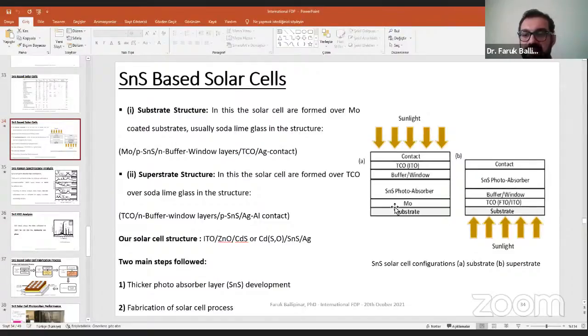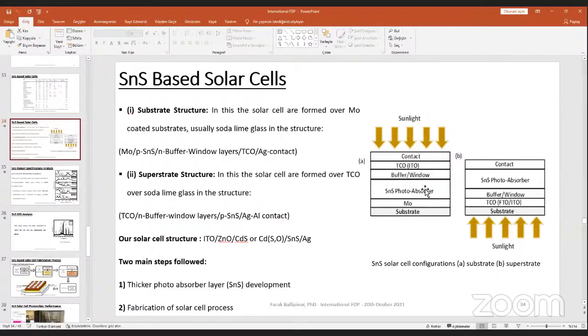Once we deposit the tin sulfide and sulfurize this substrate, we want only tin sulfide, but at the same time the sulfurization goes through the moly substrate as well. So moly sulfide might be a problem, especially for the recombination loss between these two contacts. So generally people prefer to use this superstrate structure, and the contact is not a big issue for the superstrate.